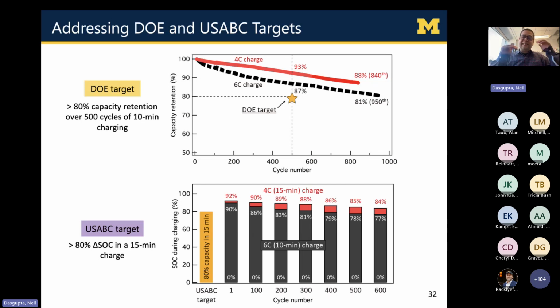So the US ABC has a slightly different metric, which talks about the delta SOC swing, right? How fast can you change it from, say, 10 to 90% or 20 to 100% state of charge? And this is where you see a lot of claims of fast charging batteries. Be cautious, because a lot of claims of fast charging battery will say, I can charge my battery in 15 minutes, but they're only talking about charging from 20 to 80% state of charge. What we see is that with this whole electrode, we can go from 0 to 92% state of charge in 15 minutes and 0 to 90% state of charge in 10 minutes.